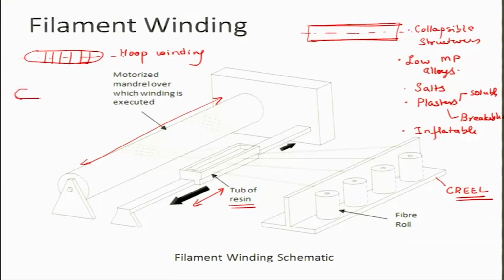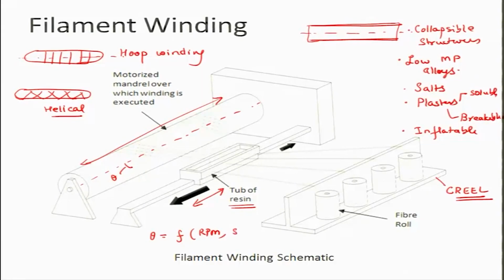Another way you can have winding is at an angle. You can have different angles, and this is angular or helical winding. If this is the axis of the mandrel and this angle is theta, this theta can be controlled by controlling two parameters. What are those two parameters? Theta is a function of RPM and this velocity v, these two things. If the RPM is extremely high, this angle will be closer to 90 degrees.